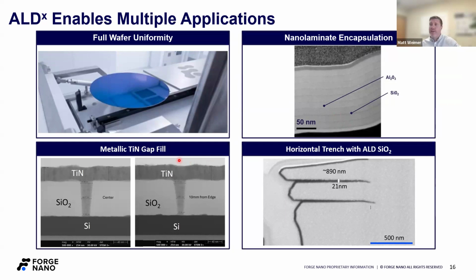Do you still get a conformal film? So this is my favorite example of how it is conformal. This is our titanium nitride film doing gap fill on silicon dioxide features. These are only about 2.5 to 1. But the fact that we're able to fill these features without a gap shows that our process is still ALD. So the cycle time on this one was right around 1.5 seconds.